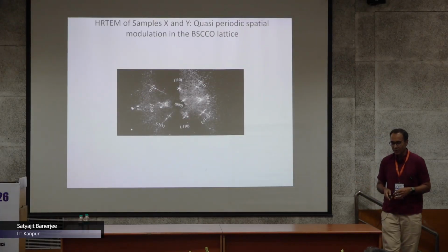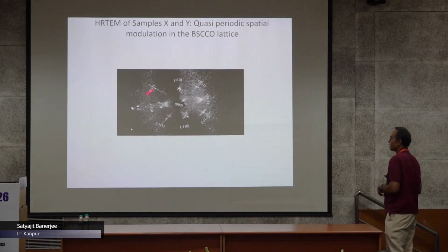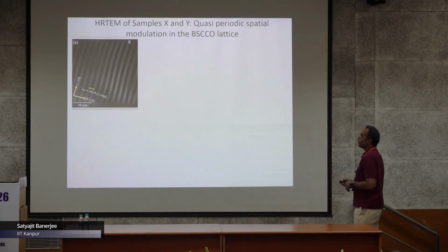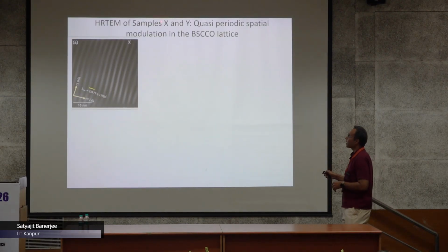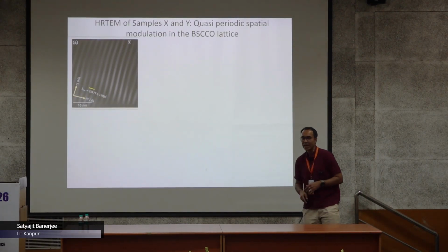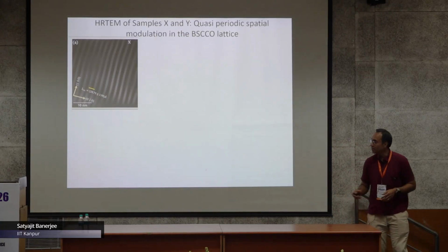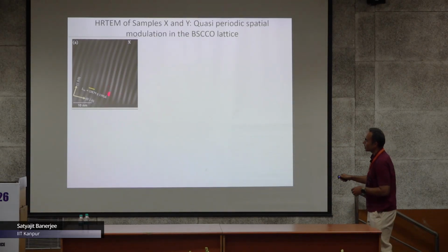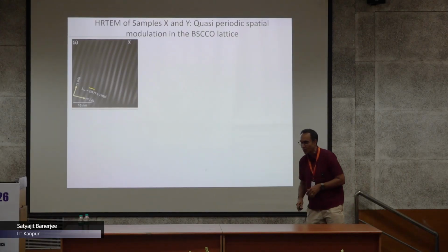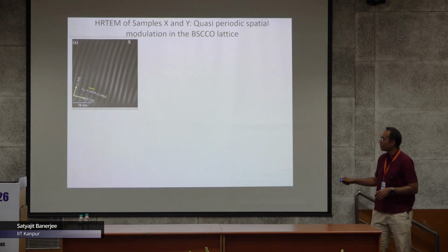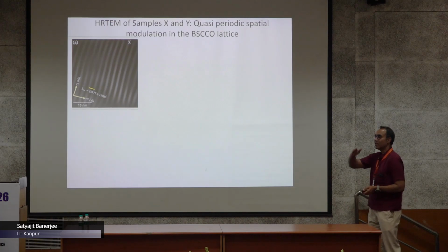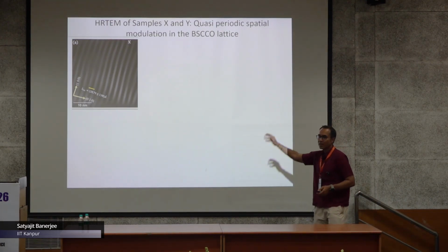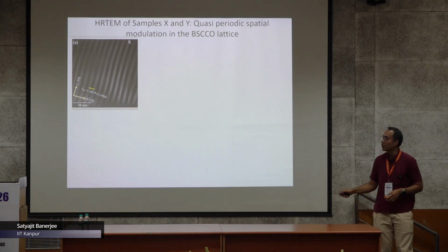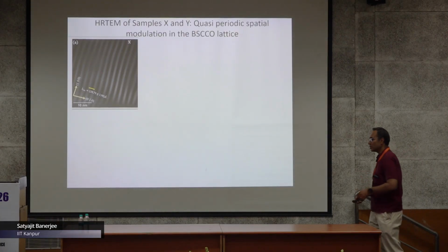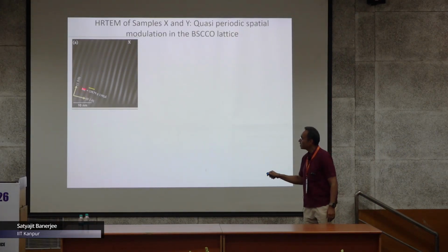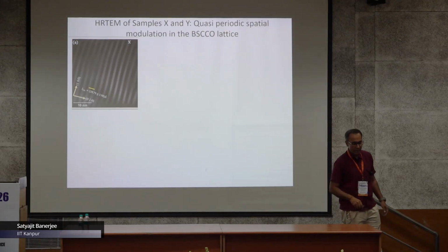The crystal is very well formed. But if you do high resolution transmission electron microscopy of sample X, you can see the atomic spots — these are the atoms of BSCCO 2223 — but over and above the atoms, you see a modulation in the atomic distribution. There is a periodic modulation in the atomic distribution inside 2223, and this period is about 28 nanometers.